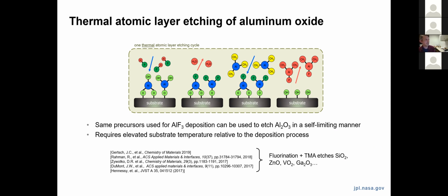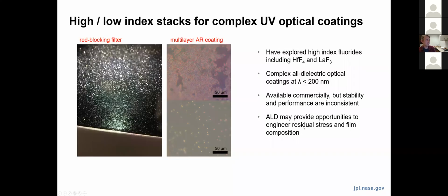Atomic layer etching, or ALE, is essentially the inverse of ALD, where again, a series of self-limiting chemical reactions can now etch material one atomic layer at a time. So we can use this approach to allow the aluminum to oxidize and then remove it in a self-limiting manner inside the ALD chamber before being coated.